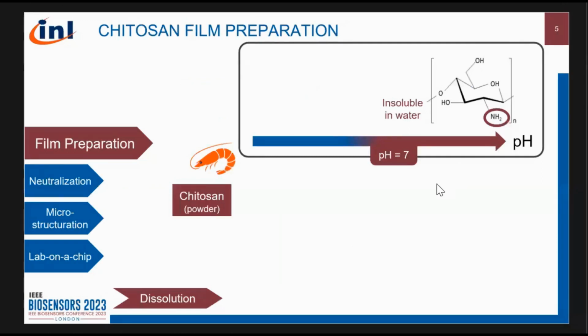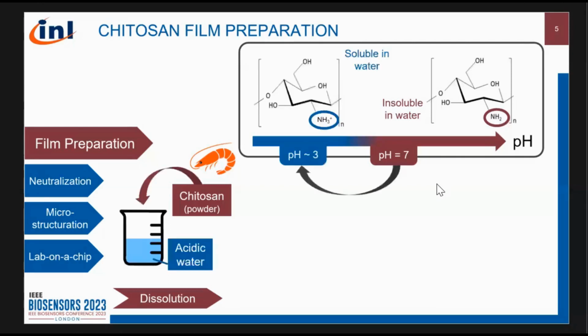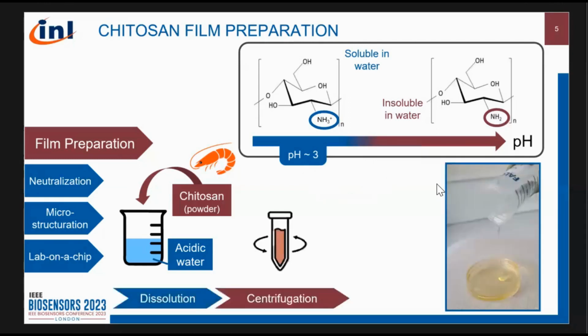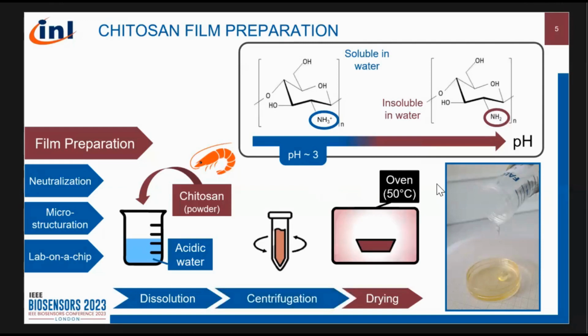So from Chitosan powder, I will present to you the protocol to fabricate a microfluidic system. We first need to dissolve the powder in solution. However, as the Chitosan is insoluble in water, we need to dissolve it in acidic solution. By bringing down the pH, we will protonate the amino group of the Chitosan, which makes it soluble. Then we centrifuge the solution to remove any bubbles, and we dry it in an oven at 50 degrees.